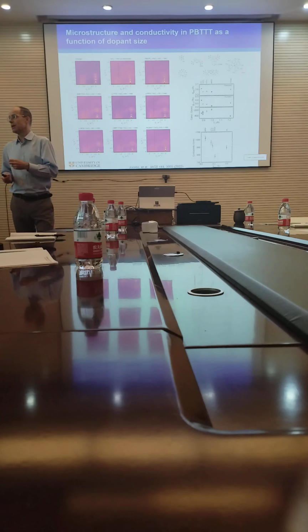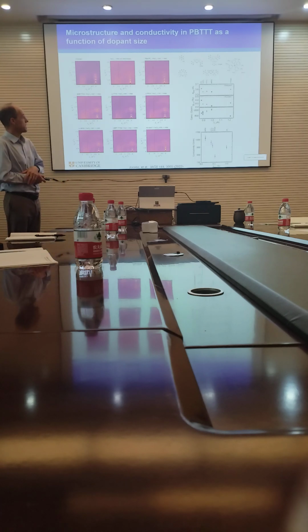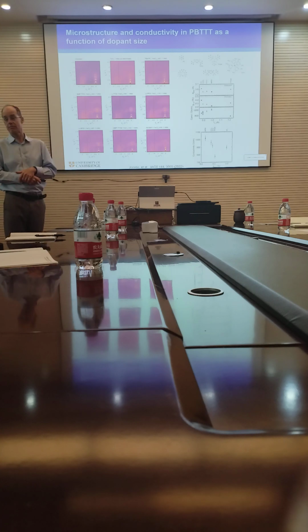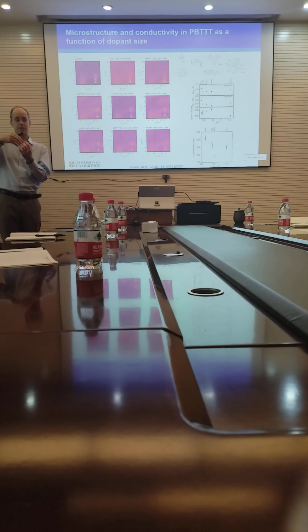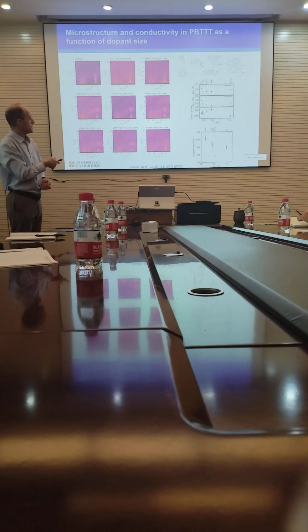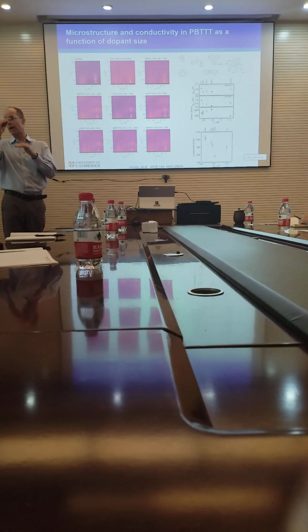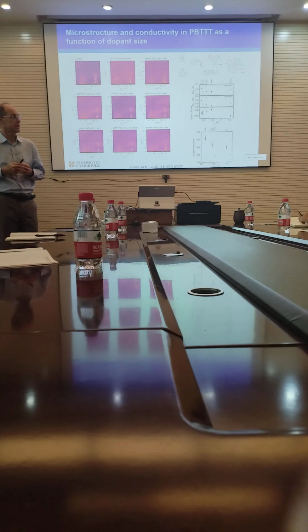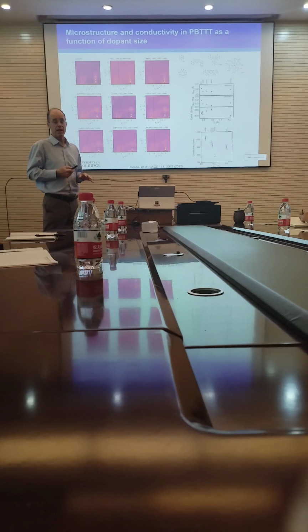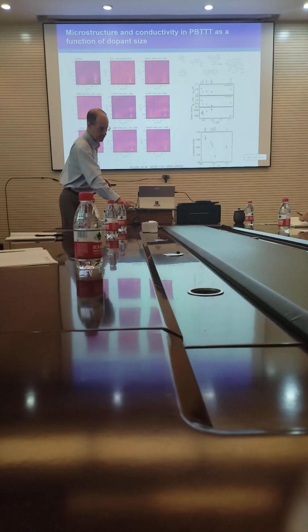What we thought would happen is that we would see the highest conductivities for the largest anions, because we thought a large anion is further away from the polymer backbone. The Coulomb attraction between the counterion and the electronic charges would be weaker than for a small anion that gets close to the backbone. But that's not what we saw. You can see that here, the conductivity is actually independent of the ion size. For all these ions, we see high conductivities between 800 and 1,000 Siemens per centimeter. So we find that the conductivity is independent of the ion size in this beautiful model system.